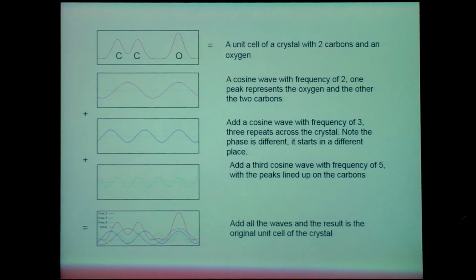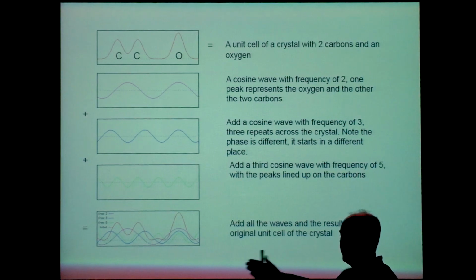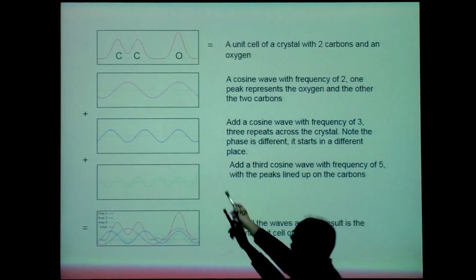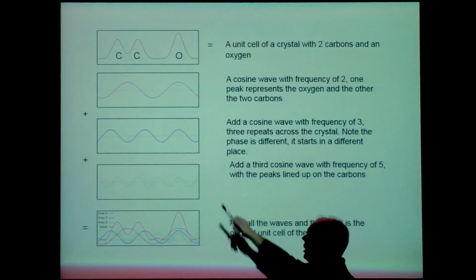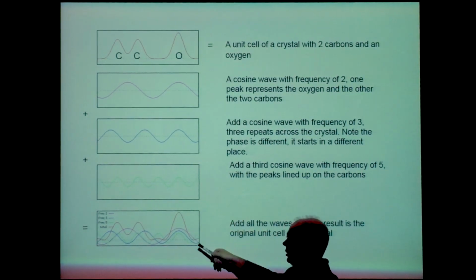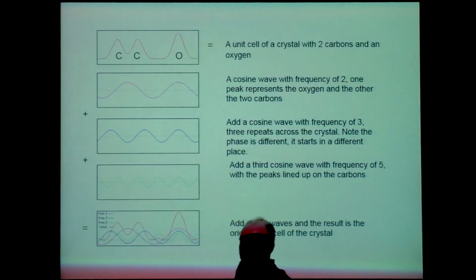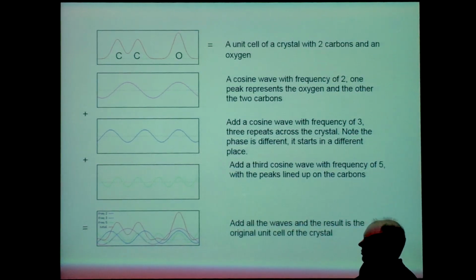Now, do you know what those frequency components relate to? We've got the HKLs we talked about in the last lecture. The higher the order of the HKLs, the higher the frequency component of these cosines that are added together. So as you get higher and higher and higher frequency, your reconstruction of that electron density becomes more and more accurate.